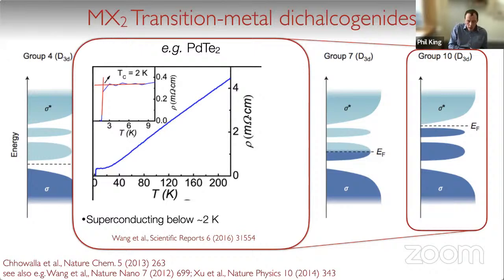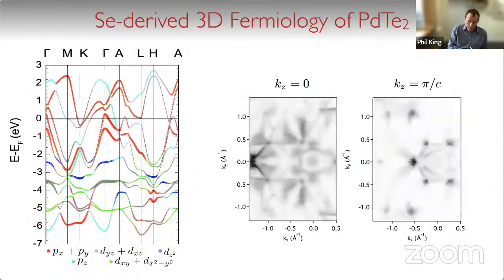But it's also really a beautiful model system for understanding the role of the p states in these TMDs in general. And that's because if you take this system, and I'm showing you on the left here density functional theory calculations from Sahid Baremi, you see that actually the weight of the d states is pushed down a couple of electron volts or so below the Fermi level. So all the states at the Fermi level here are really dominated by the chalcogen, in this case tellurium p states in the system.